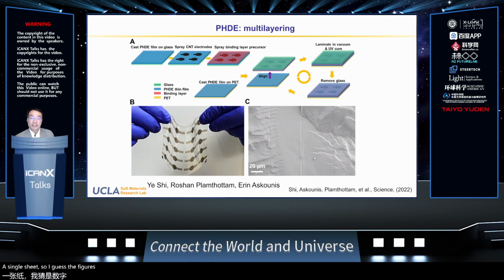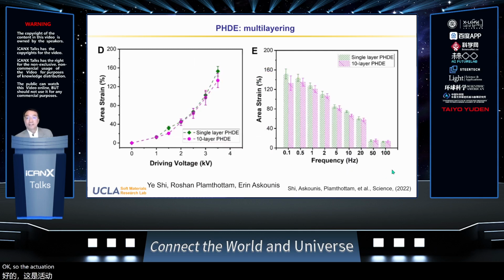Figure B shown here is a 10-layer PHDE film stacked together. We have 5 times 2 active areas in this 10-layer stack. The lower right image is the SEM of the cross section, which shows the nice interfaces. Basically, in this 10-layer stack, the overall film behaves like a single thicker PHDE layer. The actuation of this 10-layer stack is similar to a single layer PHDE film in actuation strength and also response speed. The right chart shows the green bar for the single layer and the red bar for the 10-layer stack.